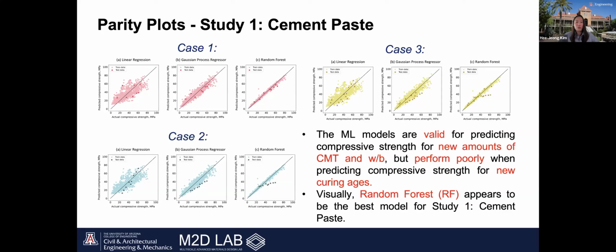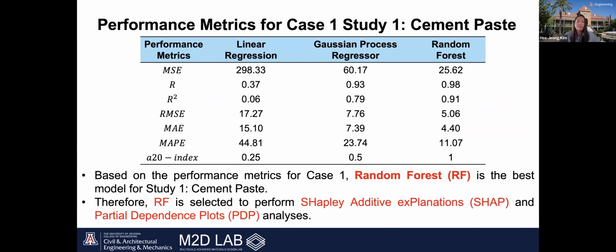However, when we introduced new curing ages, or combinations of new CMT amounts, water to binder ratios, and curing ages, the models were less accurate. They could not predict compressive strength as reliably in those cases. And among all the models, the random forest model with Bayesian hyperparameter optimization performed the best overall in case number one.